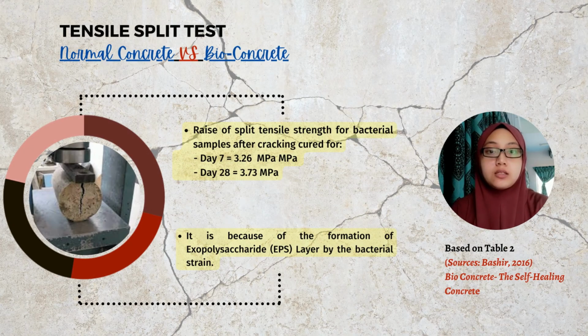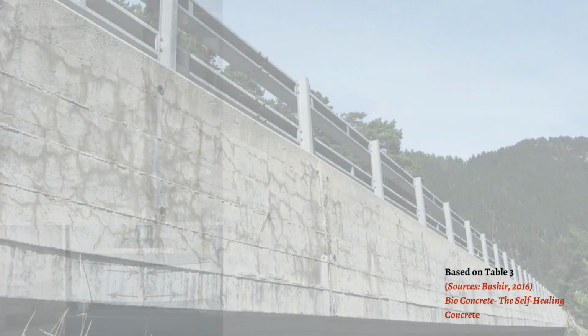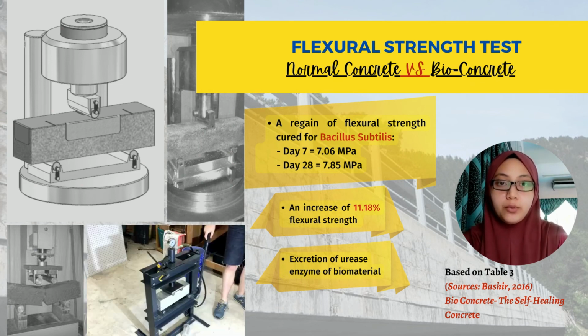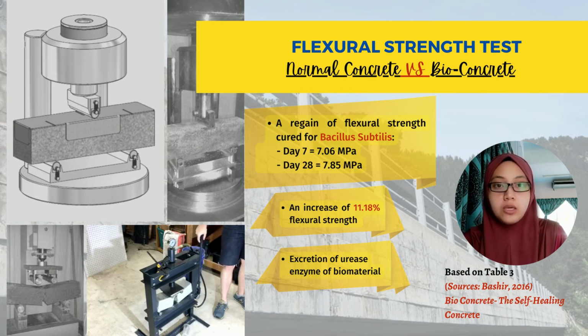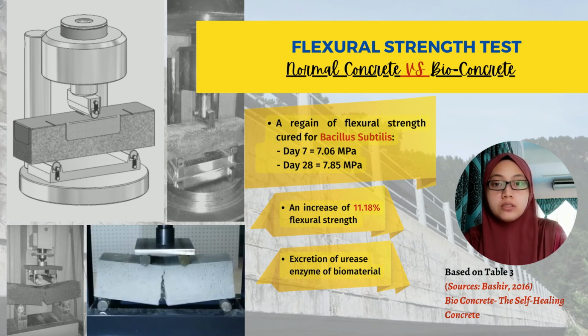Similar to the compressive strength, the split tensile strength was computed for 7 and 28 days of curing. There is an increase of 38.17% in split tensile strength for the bacterial sample of Bacillus subtilis after curing for 7 days and 14.14% for 28 days compared to the normal concrete. It is because of the formation of the EPS layer by the bacterial strain. The split tensile strength at day 28 increased to 3.73 MPa from 3.26 MPa after crack healing. There is a regain of flexural strength of 7.85 MPa for the bacterial mixed specimen of Bacillus subtilis from 7.06 MPa for the ordinary concrete sample after 28 days.